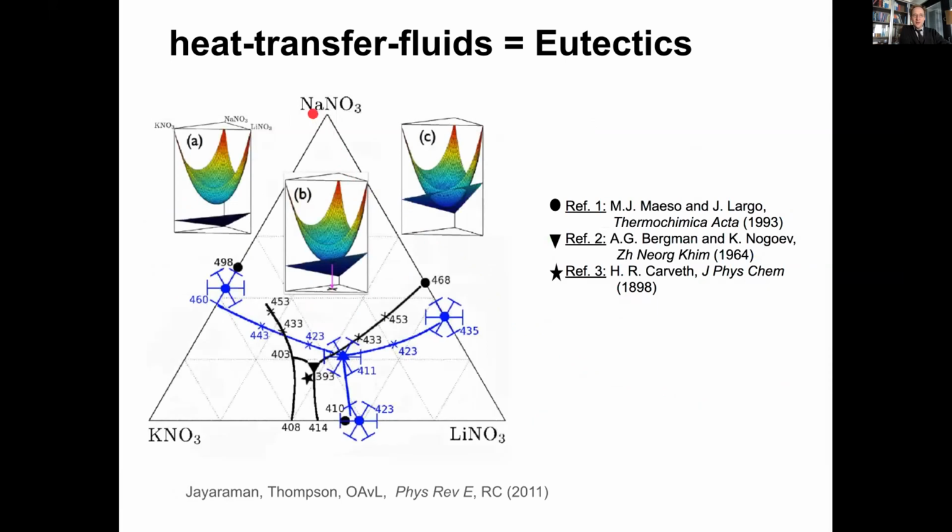Now, of course, we can do this also for sodium, potassium, and lithium. Then you have the ternary phase diagram. And on every binary diagonal, right, you can repeat this game, changing A into B while keeping the C at that current level constant. And then you can map out the predictions shown here in blue, right? So at the borders here, you have the pure binary sodium lithium. Here you have the pure binary potassium lithium. Here you have the pure binary sodium potassium. And we can also go in between, and we can even, due to the StatMech sampling, the MD sampling, include some uncertainties here, which are shown in blue.